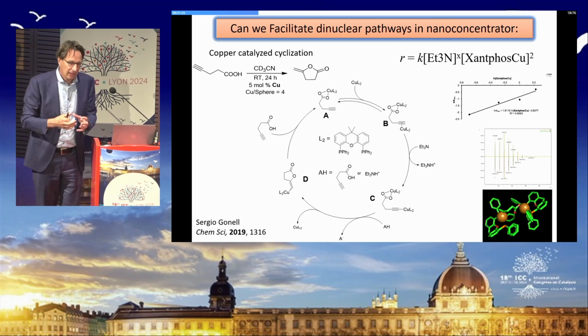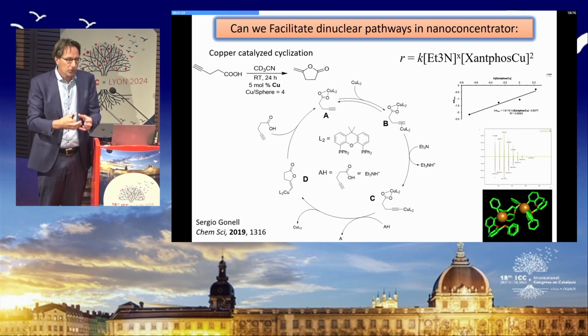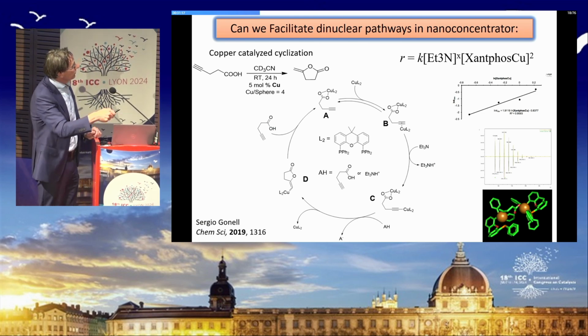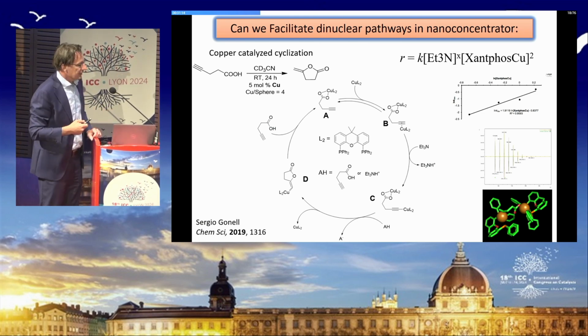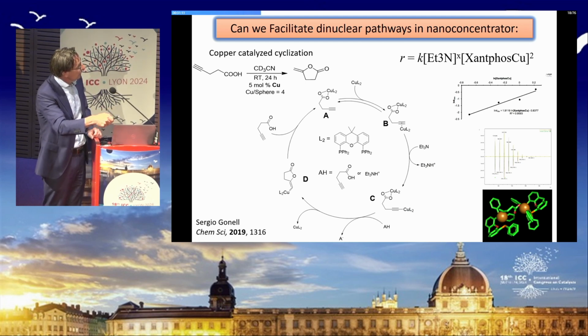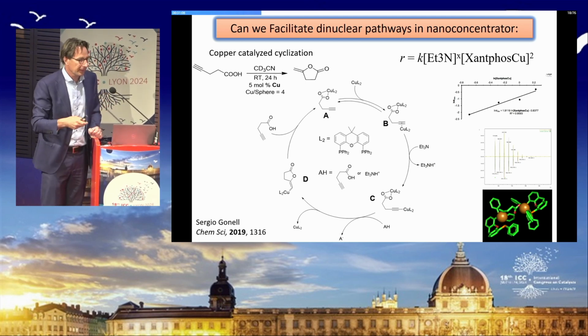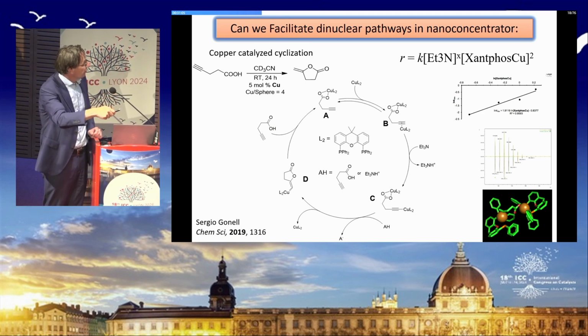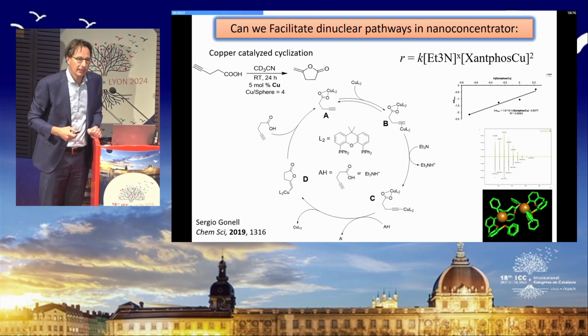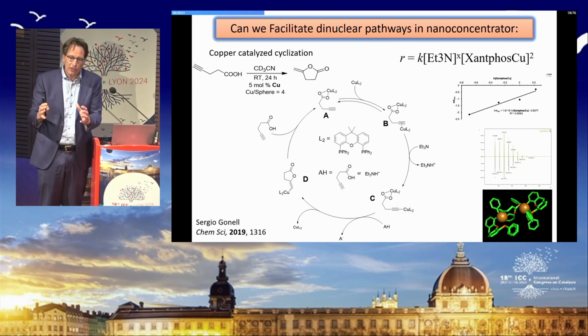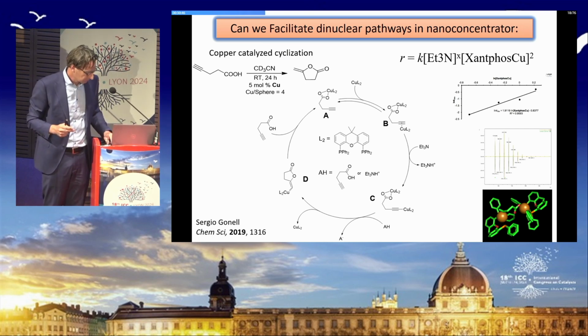Next, we also looked at can we use this to, on purpose, facilitate reactions that operate via dinuclear mechanism. And we found this catalyst, this XantphosCu catalyst, and we did all the kinetics, and we did mass spec analysis in situ, and we did deuterium experiments, and on the basis of that, we figured out that this is the mechanism where we have a pre-equilibrium before the rate determining step, and therefore we have a second order in copper complex. And if you have a higher order in metal complex, you expect if you pre-organize it, you generate a local high concentration, so the reaction should go faster.